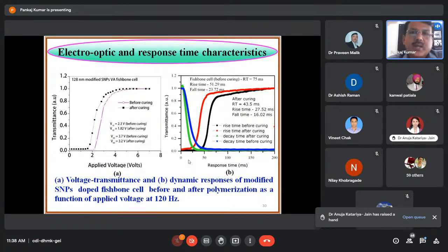Electro-optic and response time characteristics were performed in the fishbone cell also. Before curing, you can see here, this is very clear, 128 nanometer modified silicon nanoparticles were used. Before curing, you can see here the V10, that is the threshold voltage, is 2.3 volt. After curing means when we stabilize the liquid crystal molecules with the help of the UV curing, the pre-tilt angle